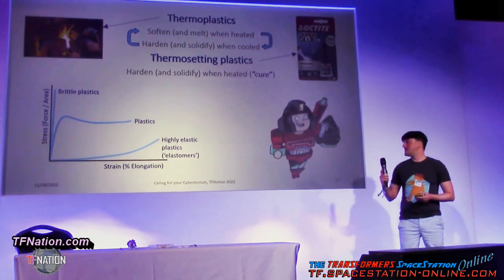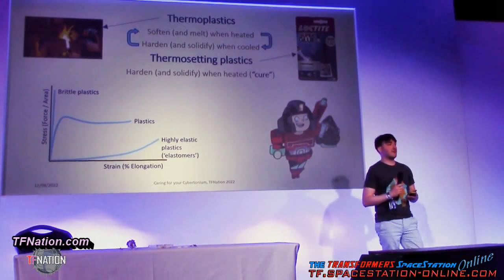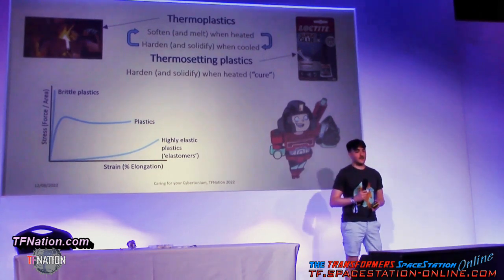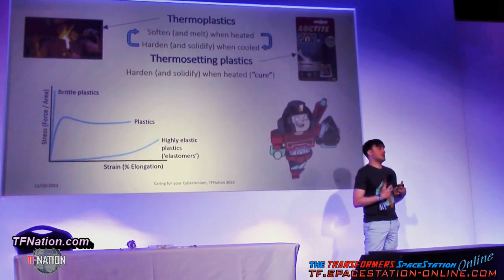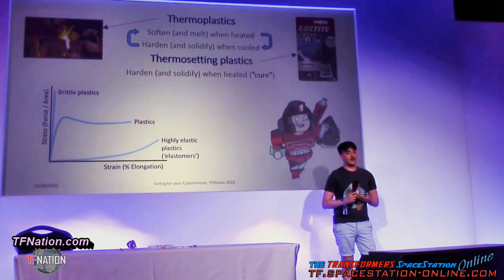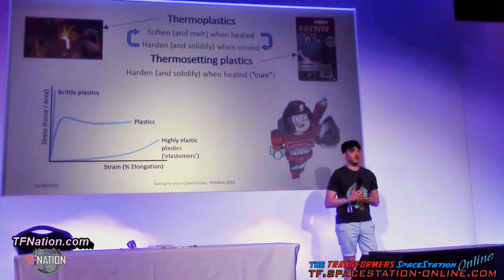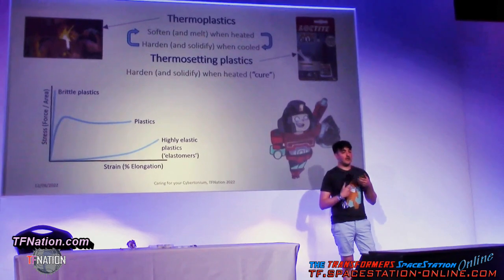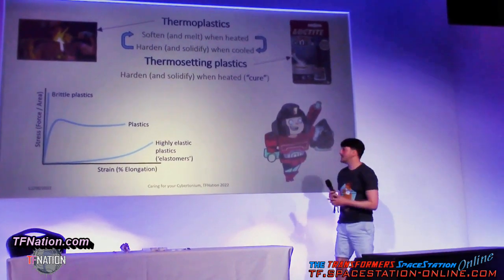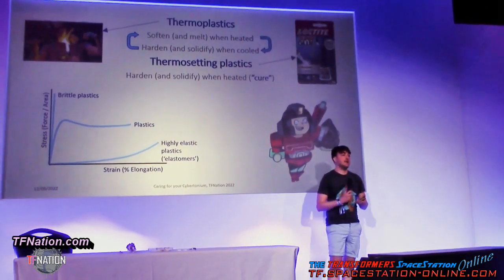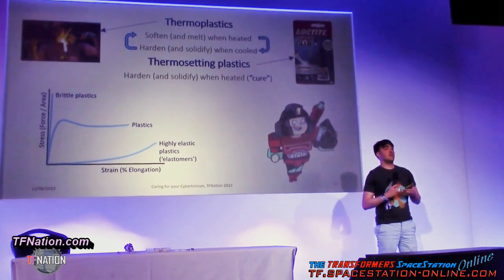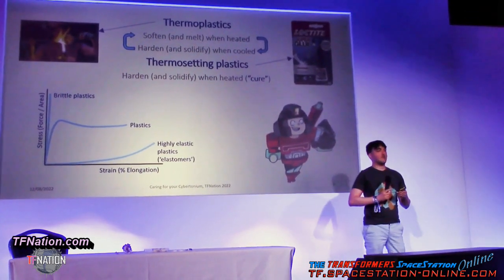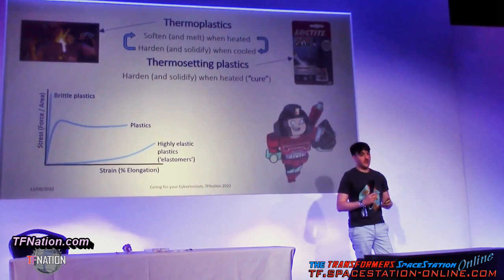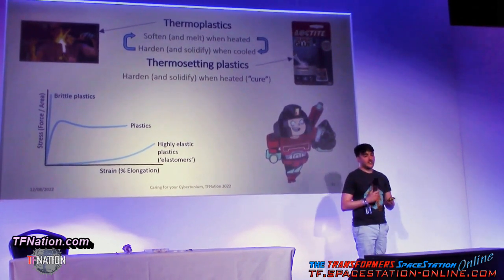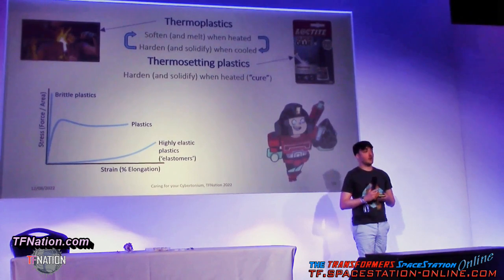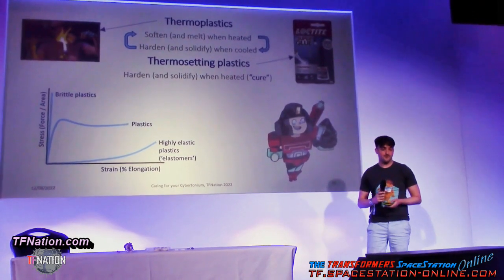So interestingly, we can see the shapes of 3 very different types or families of plastics. The one in the middle is our general plastics, so if you take a nylon part or a PVC part, you keep applying force until it reaches a peak, and when it peaks and it starts to neck, the cross-section changes, so the amount of force you need to deflect it drops, but it can take quite a lot of strain, or elongation, before it breaks.